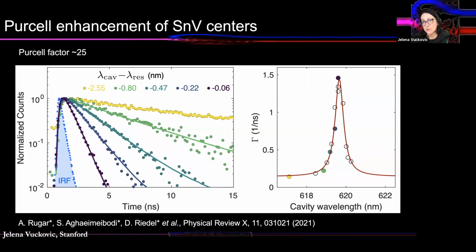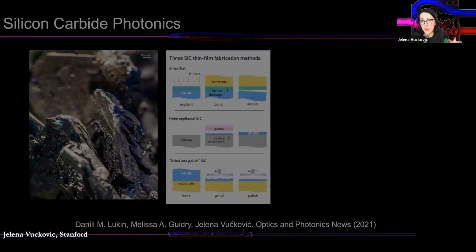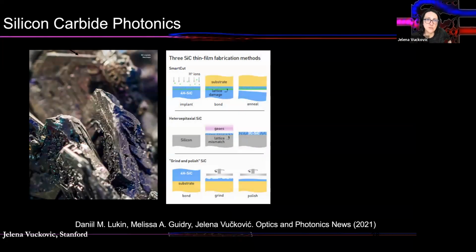This is state-of-the-art for tin vacancies in diamond, and that was published very recently by our team. And also very soon after that by the group of Mikhail Lukin at Harvard, but it's a very important step towards building scalable systems with this. So all the pieces are there. We know that we have good spin coherence for tin vacancies in diamond. We can make photonic structures and we can scale it up, and now we can move on from there. We also know how to adjust them on resonance with each other.